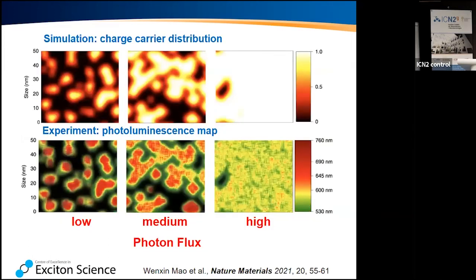And we're also working with our colleagues at the University of Sydney, and there's a theory group, and they have come up with a polaron model. So if you think of yourself as a charge carrier, a hole and an electron in an already phase segregated perovskite, the band gap in the iodide-rich phase is much smaller than in the bromide-rich. So you as a charge carrier can gain energy by going into those areas where you have your strong iodide concentration. So you'll be trapped in these areas. That's where you want to be. If you're a charge carrier, you want to be in these areas.